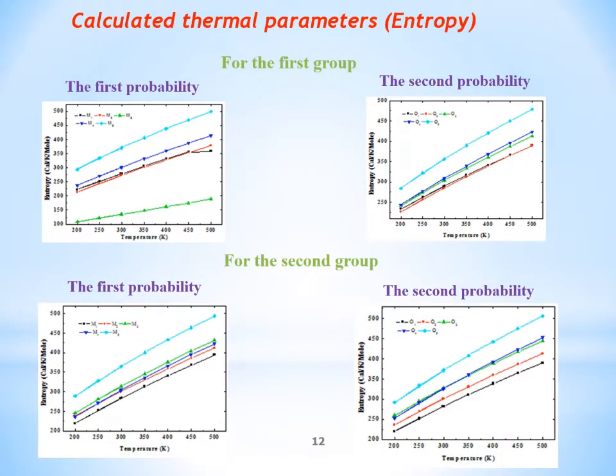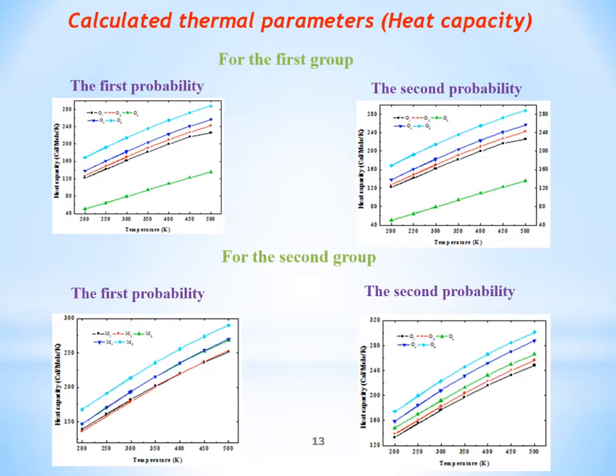Entropy expresses the disorder of the material. By studying the entropy for all probabilities in the first and second group, we find that the lowest value of entropy is also the first probability from the first group with addition of 2 units of zinc oxide, and the interaction may occur through the zinc atom. Heat capacity is defined as the amount of energy needed to increase the temperature of 1 mole of the material by 1 degree.